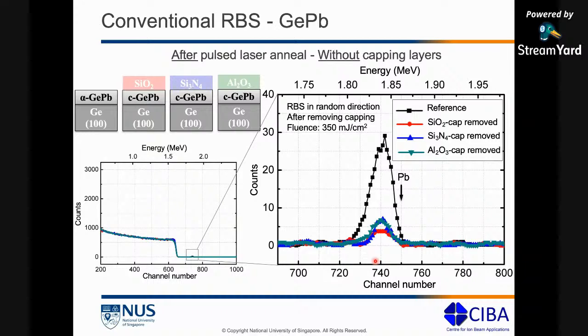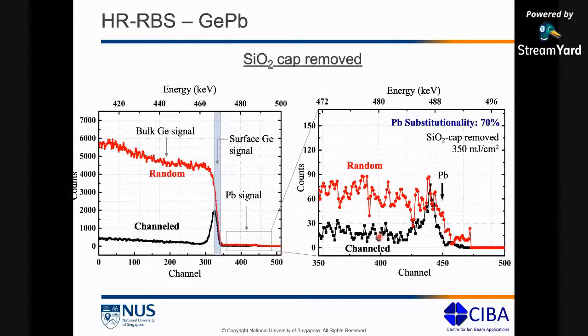And then with whatever lead we have left, we wanted to see whether this lead is in the substitutional site or the interstitial site, right? So we wanted to see whether the quality of that film with the lead being in there is good or not. So for this, we went on to do high resolution RBS measurements in channeled and random mode. This cannot be done in conventional RBS, so we have to use a high resolution RBS system to be able to resolve these lead signals.